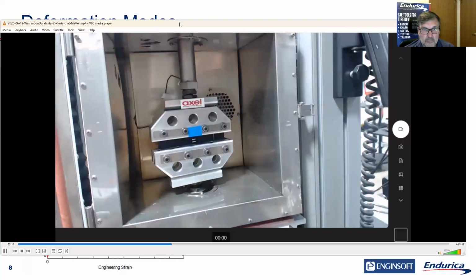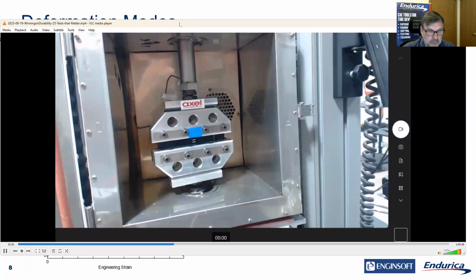When we stretch this specimen, because it's very wide and not very high, we are trying to achieve a condition where, because it's really wide and it can't move, let's just say left and right on your screen, it can't strain, all the thinning occurs in one direction. So when I stretch it, it gets thinner only front to back. There's no sucking in on the sides. Of course, there is a teeny weeny little bit, but we're going to pretend that's not happening.